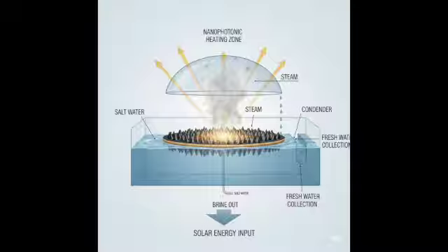Immensely. The trapped gas in the pores significantly lowers the overall effective thermal conductivity of the membrane structure. This helps maintain that desired reverse temperature profile by preventing the photothermal heat from immediately conducting back into the bulk feed. Makes sense. Finally, stability.